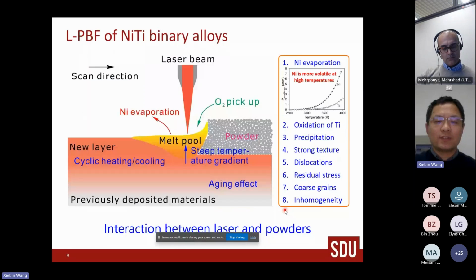In order to achieve this, firstly, we analyze the interaction between laser and nickel titanium powders. And we found that a lot of phenomena will occur during this process. For example, nickel evaporation, because nickel has a lower melting point than titanium. So at high temperatures, nickel is more easy to evaporate as compared with titanium.